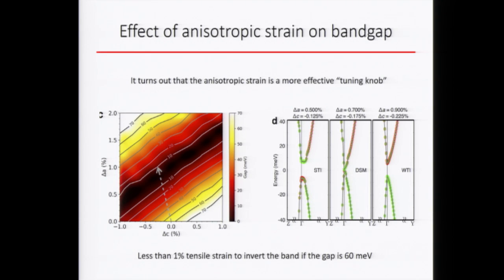Might not be helpful, but did you also think about chemical pressure, doping, something? I mean, perhaps that would move you along the isotropic direction, so that wouldn't help. But it wouldn't seem to be so hard. You put half in or something. Right, we thought about that. It just makes it disordered. You also introduce more carriers, and it turns out that the effect we're trying to see, you see the biggest effect with the smaller amount of carriers, closer to the band edge.